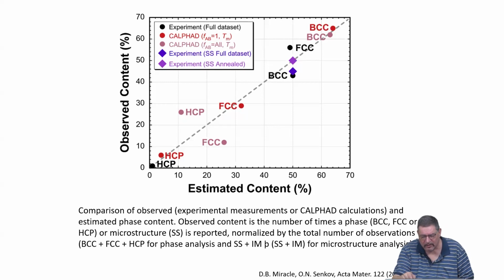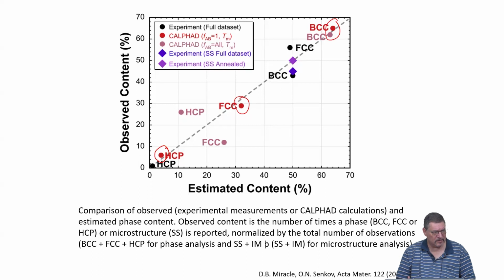And you see that yeah, obviously the fully assessed ones are the ones which are better, because then you really can predict, and Calphad is working great, so you can rely on the outcome of Calphad calculations, as you can nicely see when you compare these here. But if not all of the binaries have been assessed, then obviously there are larger deviations possible. All in all, the structure in, structure out approach works.